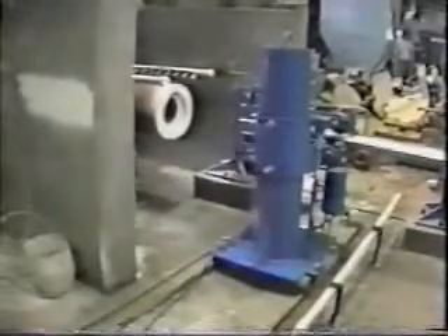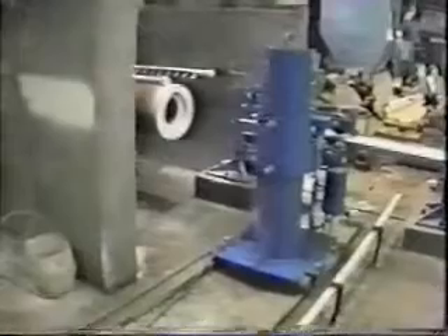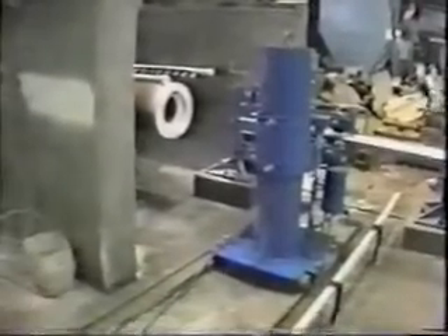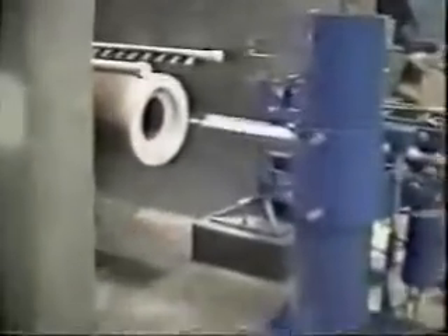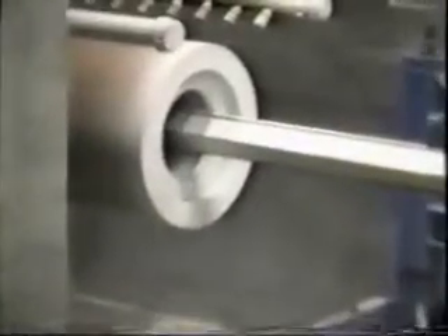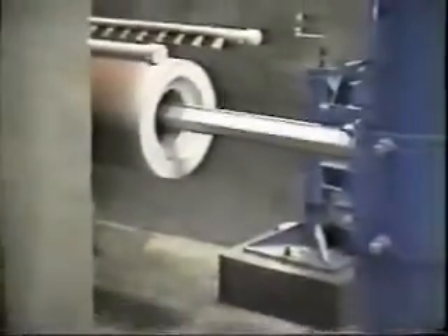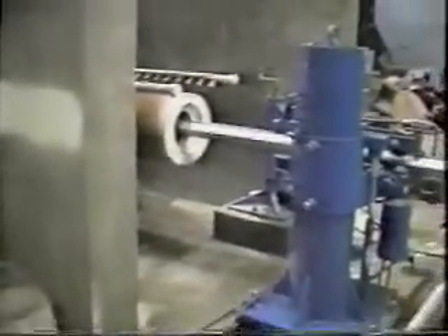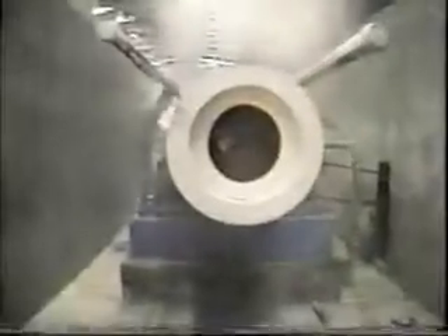There is a time delay before the spray nozzle comes on to allow the spray pattern to fully develop before it enters the mold. The lance proceeds through the mold until it reaches the pouring end of the casting machine. Three passes with 2 coatings each are used to develop a 1/32 inch coating in this mold.